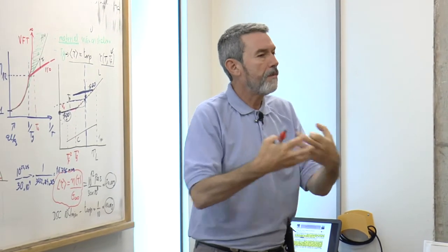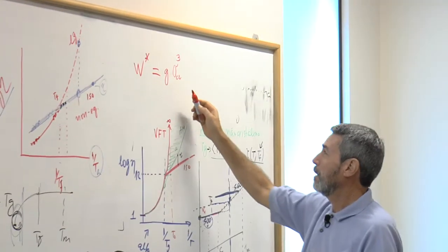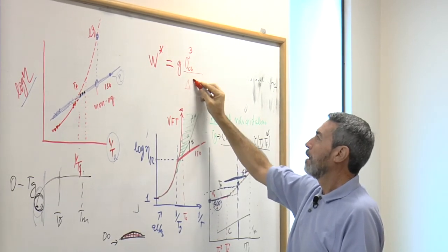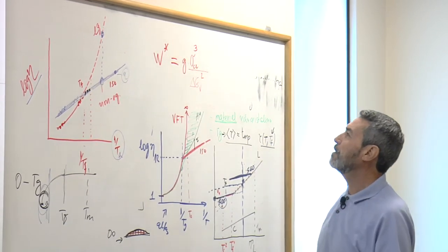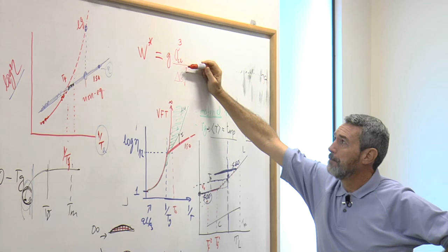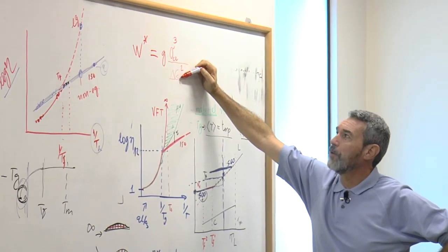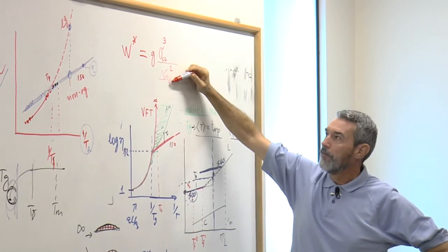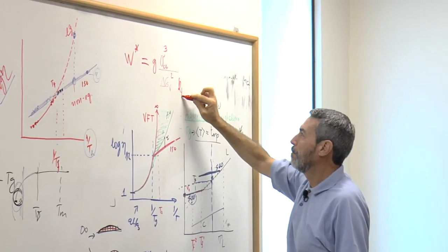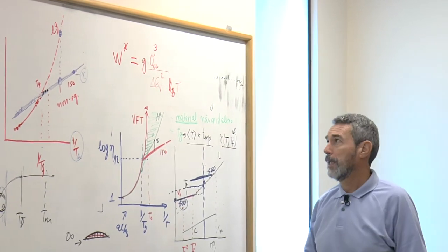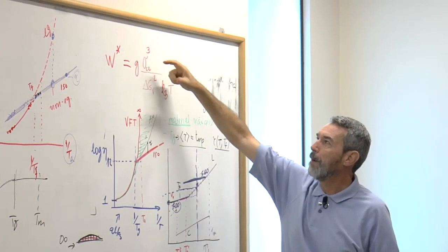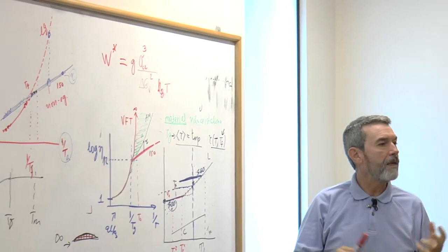So this is a positive contribution to the overall energy, divided by the difference in free energy, the difference between the energy of the crystal and glass per unit volume, squared. And then we have kT, the Boltzmann constant and the actual temperature. So it's the balance of these quantities that is the thermodynamic barrier.